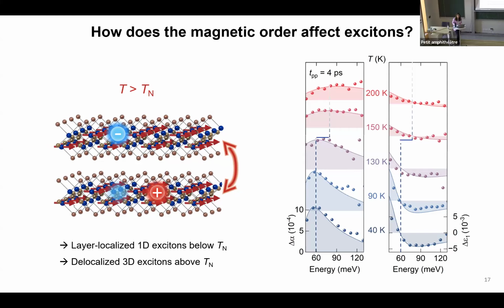And does this kind of orientation also matter for their decay rate? It matters because, you know what? When your electron is farther from the hole, it has a harder time finding it and recombining with it, such that you go back to the ground state, right? However, when they are closer to each other, the recombination of the electron and hole pairs can take place more easily, simply because of the spatial delocalization.